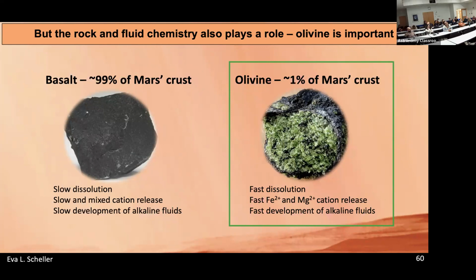And through these pretty well-known geochemical constraints, we know we're going to get much faster dissolution, iron and magnesium cation release, and fast development of alkaline fluids in the olivine terrains, and much slower dissolution, mixed cation release, and slower development of alkaline fluids in the basalts. Now, these kinetics are exacerbated if the water activity level is lower, okay? So we may be able to get some constraints on that as well. But in general, it's not surprising to find that ultramafic terrains are driving the carbonation on Mars.